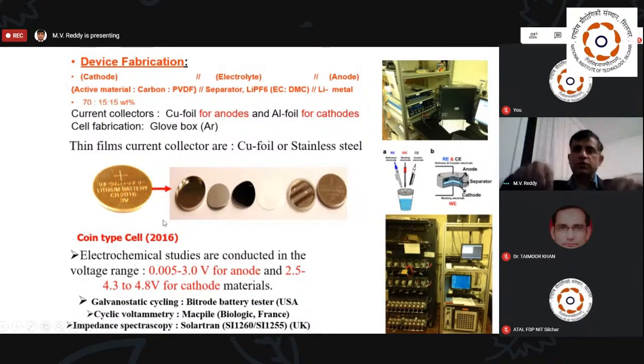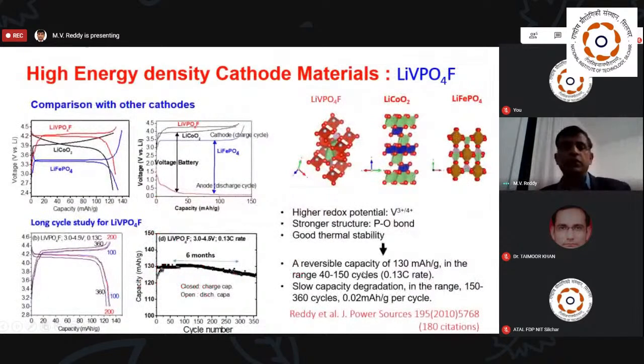Remember, once the cell is good, you can do performance studies, whatever type of studies you want. I told you that using this setup, you can do fast charges or slow charges. You can monitor the voltage as a function of time, and from that, you can calculate the capacity. This battery has run for nearly 6 months with reasonably good stability. If it is bad, it will die within 50 cycles, which indicates the material is not really good.